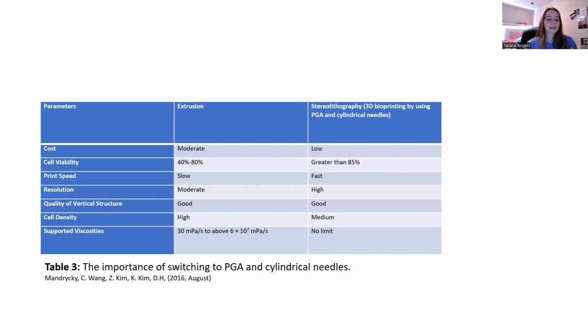And in this PowerPoint presentation, I've gone over the benefits of increased cell viability for using cylindrical needles in PGA and the benefits of CellLink's PGA and cylindrical needles. Like I said before, the cost of using these is low and the cell viability typically ranges at around 85%. The print speed is a lot faster than our previous speed, which is the extrusion based printing, and the resolution that we can print from these cells is pretty high, and the quality of the lattice is good as well as it was previously with extrusion based printing.